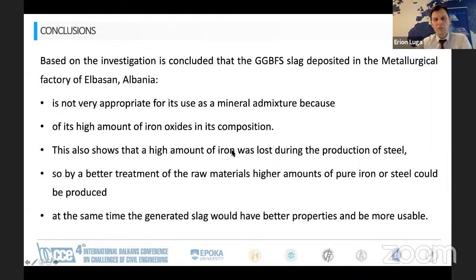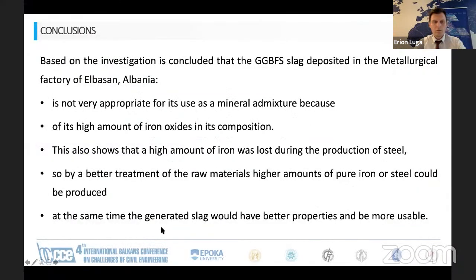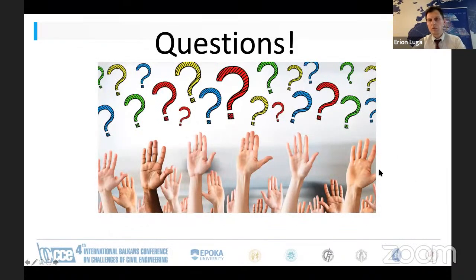This also shows that a high amount of iron was lost during the production of steel. So this oxide should be in the other part of the production, not as waste. By a better treatment of the raw materials, higher amounts of pure iron or steel could be produced. At the same time, the generated slag would have better properties and be more usable. So this was our investigation and our conclusions. We would be glad to have your questions.